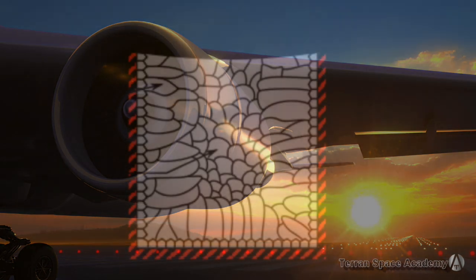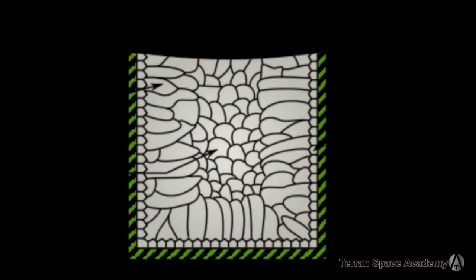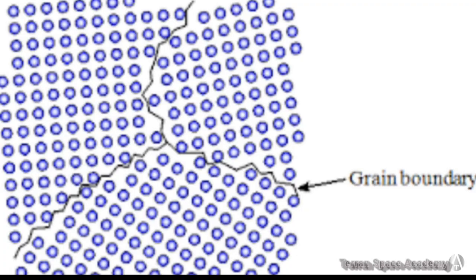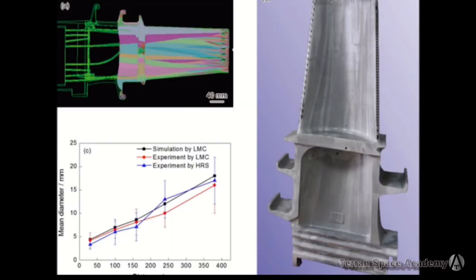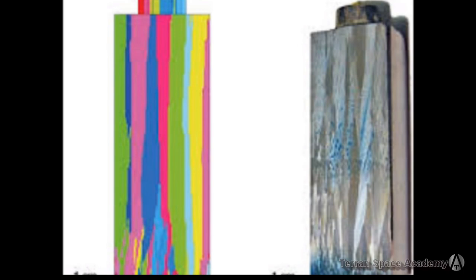Now, crystals form as alloys go from molten to solid. These crystals are just tens of microns across and are randomly oriented. At high temperature and stress, these crystals start to slide against each other, and any impurities create weak points between crystals. This is what causes creep. The engineers and metallurgists soon started finding ways to make all the crystals line up in one direction, with their long axis in line with the stress. Other alloys of nickel are possible also.